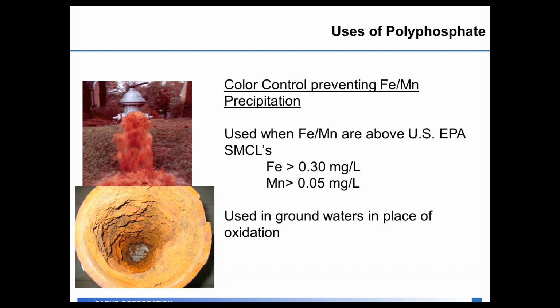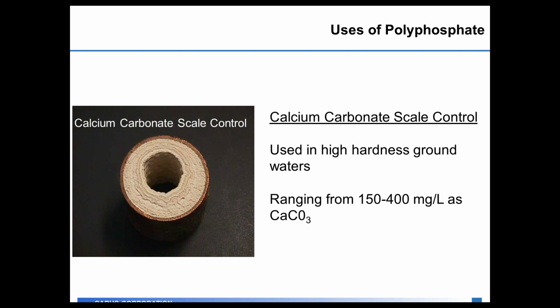Typically, the place you see the most sequestering used and polyphosphates used is in groundwater plants where they're doing no oxidation and no filtration before they send the water out the door to the consumer. In place of that oxidation and filtration, they use the polyphosphate to sequester the mineral content. The other major use is calcium carbonate scale control. Anytime you have a high hardness water, you have a chance for having calcium carbonate scale. As you increase your pH, you increase the likelihood that calcium carbonate scaling will increase in the distribution system. Anywhere from a range of 150 to 400 milligrams per liter of calcium carbonate can cause scaling issues like you see in the picture, and polyphosphates will help prevent that scaling from getting that bad.